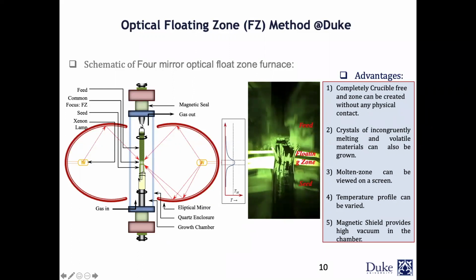And then the seed rod, which could be a compound that we've grown before from the same family, or a very dense ceramic, is sitting here. The feed rod from the top starts to move down. When it gets to the hot zone, it starts to melt, and because of the viscosity, it attaches to the other compound. By moving, we can go through the zone and come out of the zone, and the material solidifies, crystallization.